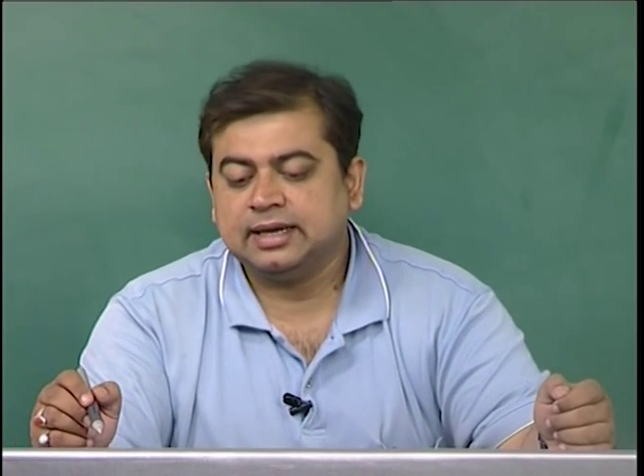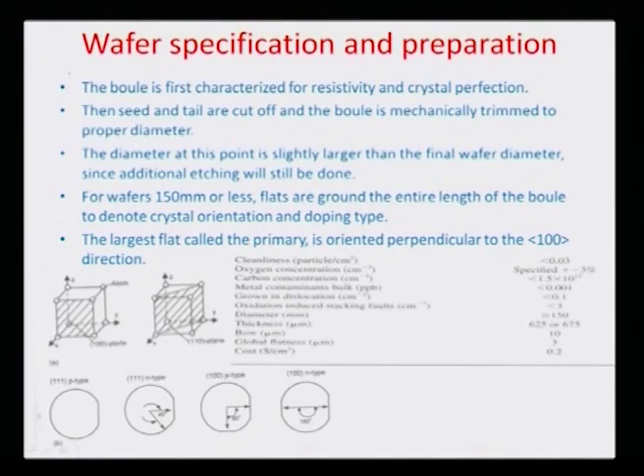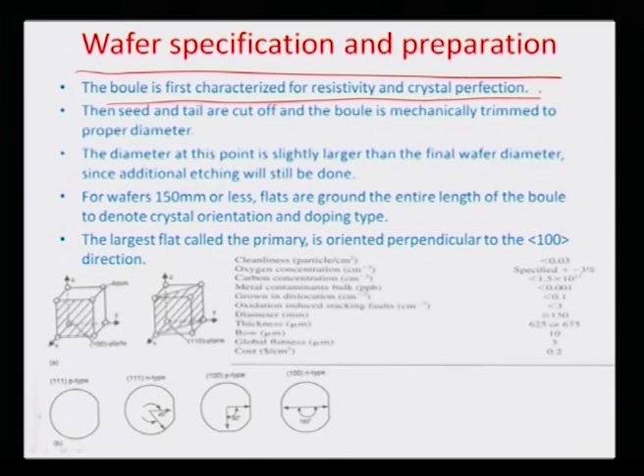Let us also look a little bit into the wafer specifications of silicon wafers, and essentially how they are prepared from the boule, which is obtained either by Czochralski's method or by the float zone method. So the boule is first characterized for resistivity and crystal perfection, and these are done by various electrical tests on the boule. Then the seed and tail are cut off the boule, and it is mechanically trimmed to proper diameter. And then finally, there is a finish trimming operation onto the final wafer diameter, since additional etching will still need to be done on those boules. Okay, so for wafers